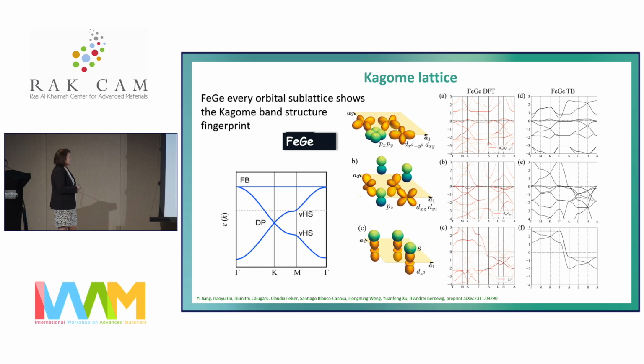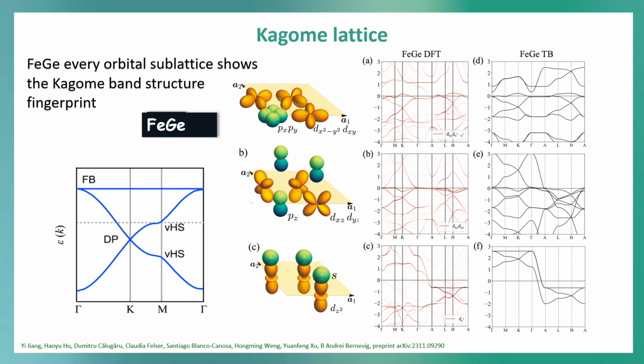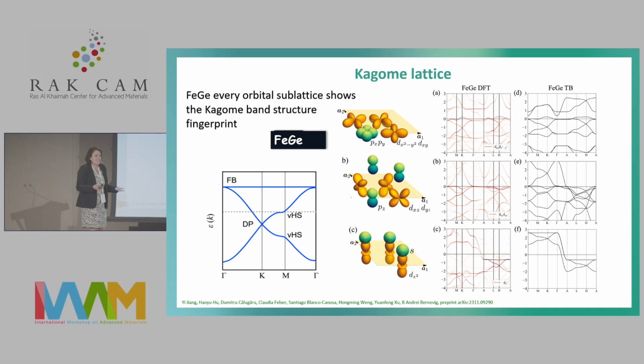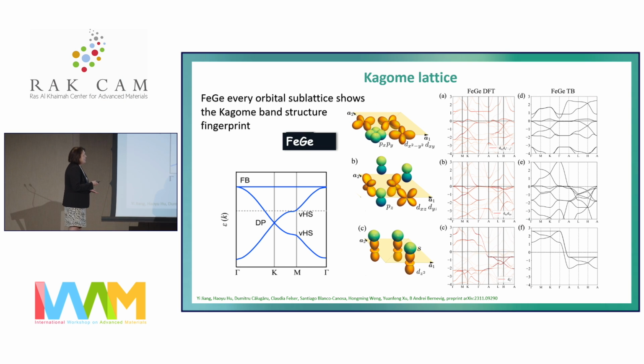Every theoretician likes to do models with s electrons, but reality is more complex. So in a magnetic material, you have d and p electrons. And indeed, we find, as you see very nicely in the tight binding model as well as in the real band structure, always the same fingerprint. It looks like the electronic structure is only made of flat bands, Van Hove singularities, and crossing points. So there should be a lot of interesting physics in this compound, which was not seen before, okay? So here we even have this interesting physics at the Fermi energy.